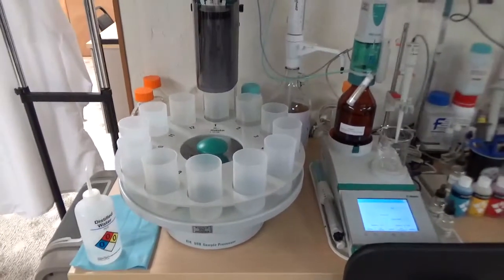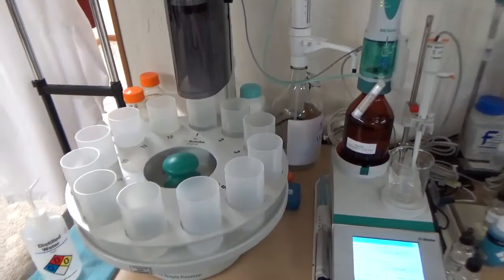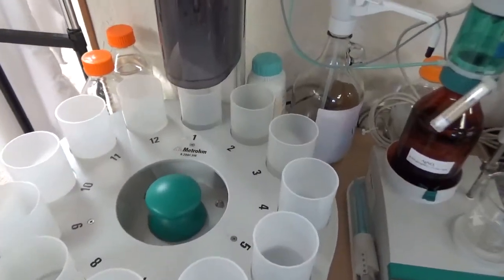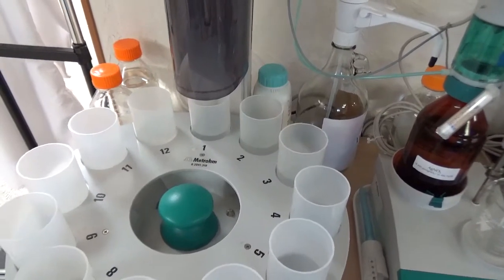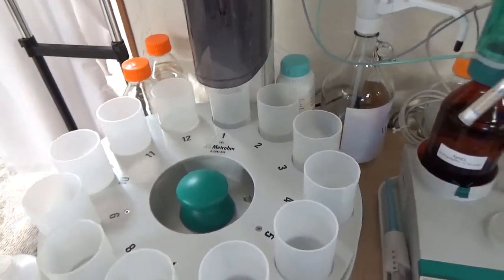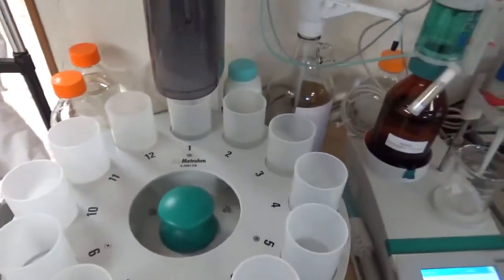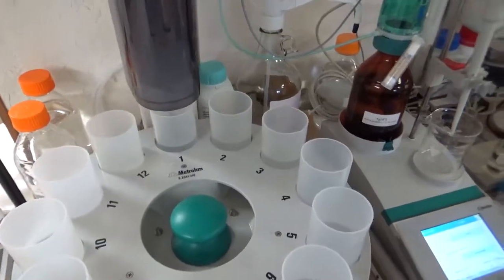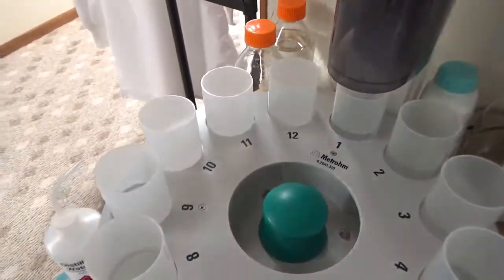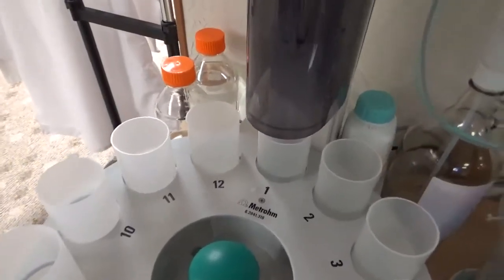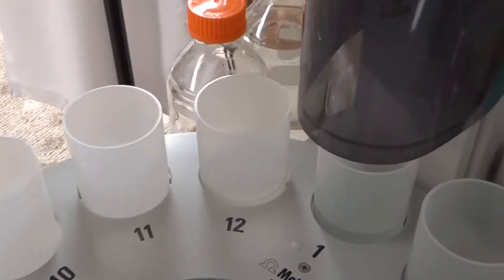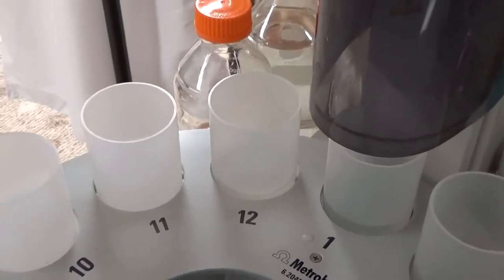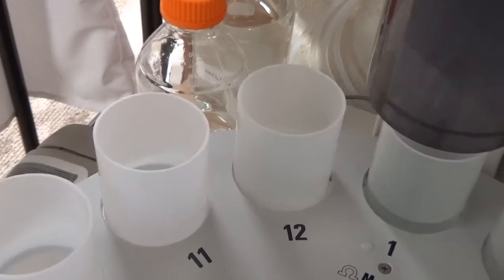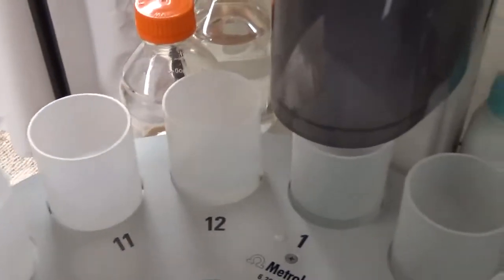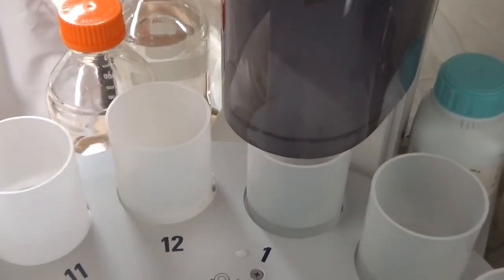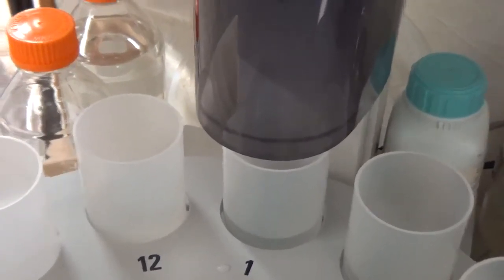It comes with a rack containing 12 samples, and then we have plastic sample cups from station 1 to station 12. Up to 10 samples can be loaded in this rack to do automated titration for chloride content from position 1 to position 10. And then 11 and 12 are used for rinsing the electrode and the burette and cleaning the electrode and the burette respectively. Station 11 just rinses the electrode, distilled water comes and rinses the electrode, and station 12 has distilled water in it where the electrode goes and it cleans the electrode.